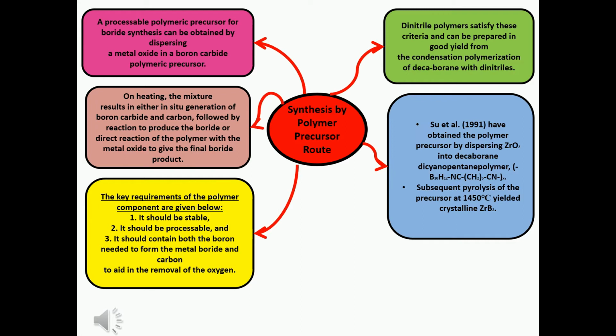The key requirements of the polymer component are given below. 1. It should be stable. 2. It should be processable, and 3. It should contain both the boron needed to form the metal boride and carbon to aid in the removal of the oxygen. Dinitrile polymers satisfy these criteria and can be prepared in good yield from the condensation polymerization of decaborane with dinitriles. Su, 1991, have obtained the polymer precursor by dispersing zirconium oxide into decaborane dicyanopentane polymer. Subsequent pyrolysis of the precursor at 1450 degrees Celsius yielded crystalline zirconium diboride.